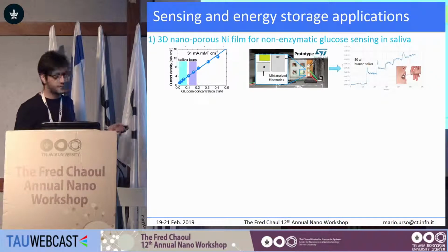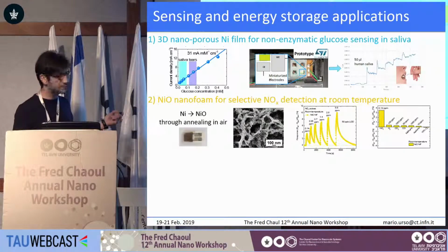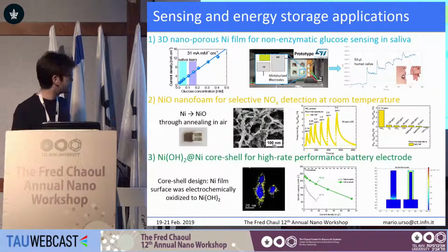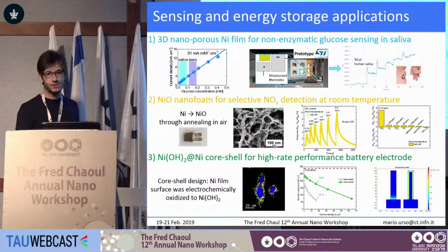But we can also modify the surface of the nickel nanoparticles by transforming them into nickel oxide nanoparticles, and in this case we were able to detect nitrogen oxide at room temperature, and we can also realize some nice core-shell architectures. In this case we take advantage of the thin nickel hydroxide shell and the conductive nickel core to get higher specific capacity and thus high rate performance for batteries and in general energy storage applications. For other information, come to my poster, which is number 33, and it's for some reason the smallest one, so you can't miss it. Thank you.